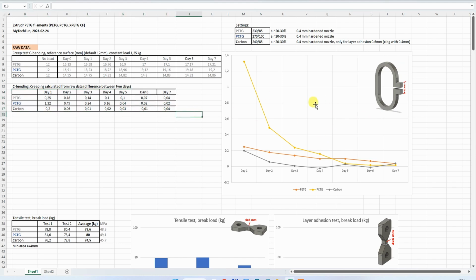And if you analyze this on this graph, we can see that PCTG had the biggest creeping in the first maybe 2-3 days, and only after 4 days it stopped with the deformation. The best in this test was the carbon version of the PETG. Basically, almost after the first day it stopped with the deformation. There are small negative values here, but that may be inaccuracy in measuring.